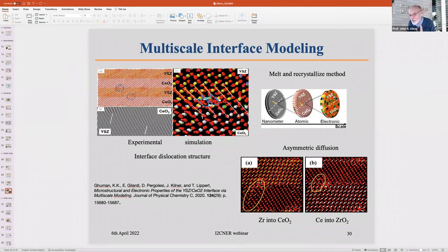Now, you might say that this is already an ionic conductor and a mixed conductor with the ceria, but between the fluorite and the perovskite, I don't know of many studies that have gone on. There have been quite a lot of studies of the interreaction, because what often happens at these interfaces is that you get the formation of a blocking phase, and the problem is how to get rid of it. For instance, if you put LSC onto YSZ, it immediately forms lanthanum zirconate, which is a poor conductor and a blocking phase. So I think it's a rich area to get into.